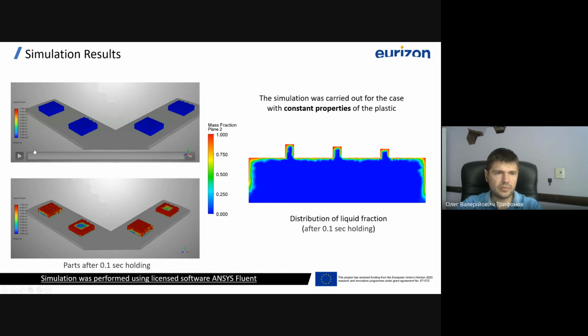And if we look at this screen, we can see the simulation of the melting process. To define the influence of temperature-dependent properties, we have simulated two cases. The first case is application of the real distribution of temperature and flow field inside the chamber, but constant properties of the plastic. And the second, more complex, is real temperature and velocity distribution and temperature-dependent properties.